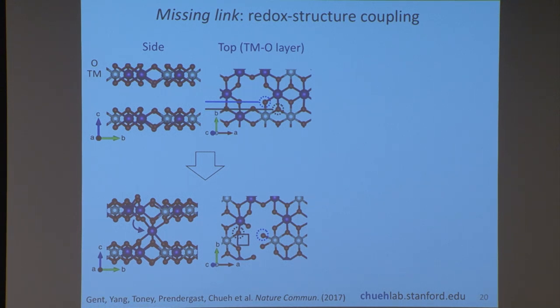If you take one of these layer structures, again, metal, oxygen, lithium layers, and you empty all of the lithium layer here, the top is the pristine material. So you also see holes in the metal layer. That is because that's where the lithium used to sit, in the lithium that we have overstuffed into the material. But that's not what happens in reality. What happens in reality is that some of the metals are happier if they sit in the lithium layer because they have almost the same atomic radius. This is known as cation migration. Some of the metal, it could be nickel, manganese, or cobalt, will actually migrate from the transition metal layer into the lithium layer, where the lithium is supposed to go.